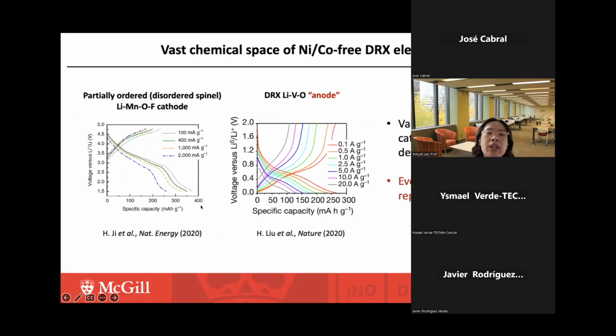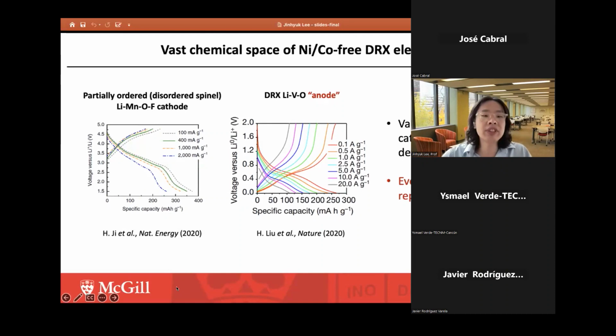So, I would like to say that the chemical space of these nickel and cobalt-free DRX cathode materials is really, really large. And now people have developed the so-called partially ordered DRX material, a partially disordered spinel that delivers ultra-high capacity above 360 milliampere hours per gram. And interestingly, in 2020, a group of scientists at UC San Diego developed a DRX lithium vanadium oxide anode, instead of the cathodes that have been developed so far.